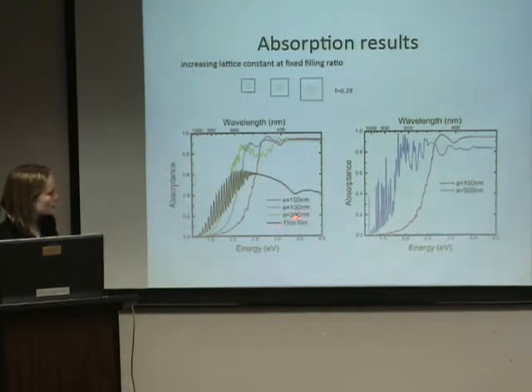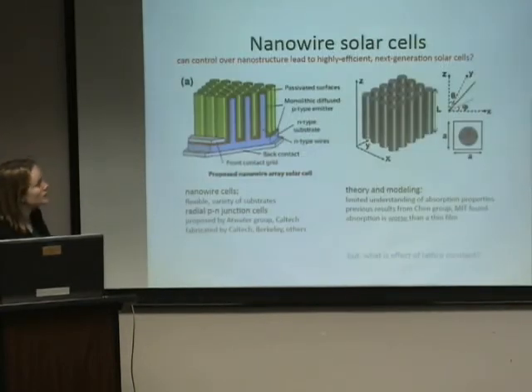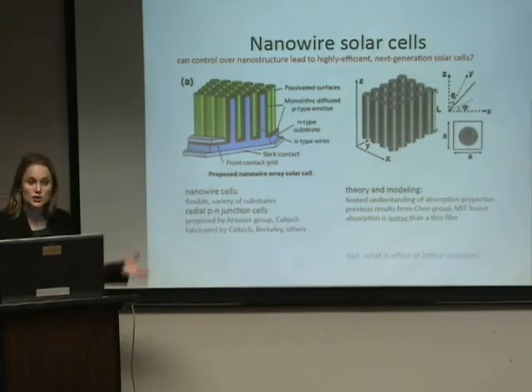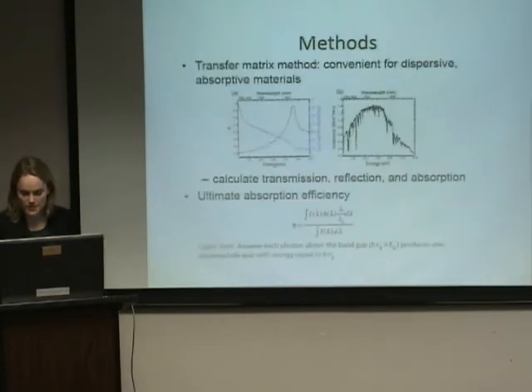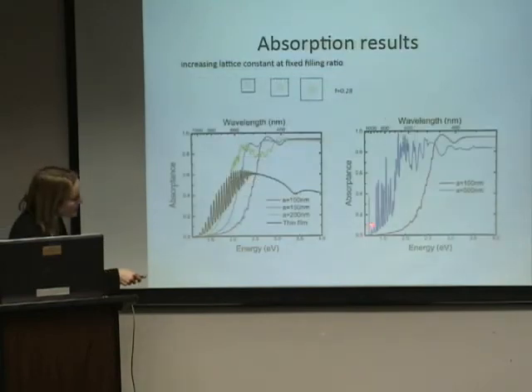If we go even further, something else interesting happens. If you make your wires quite a bit bigger, so 500 nanometers big, here again, this red line is repeated just to give you the reference. For the very big lattice constant, you get a large shift over, and you also get these resonant peaks here. These peaks that you see in the spectrum are actually a known behavior for photonic crystals. So after all, our rods are basically a photonic crystal. It's a 2D periodic structure. And there are certain modes that you can excite that have been studied that give you resonant peaks and extra enhancement. So each of these peaks gives you extra enhancement in the spectrum.